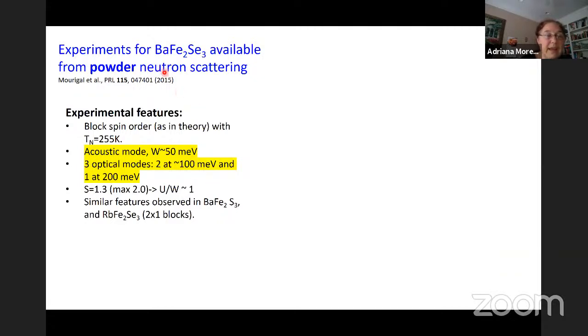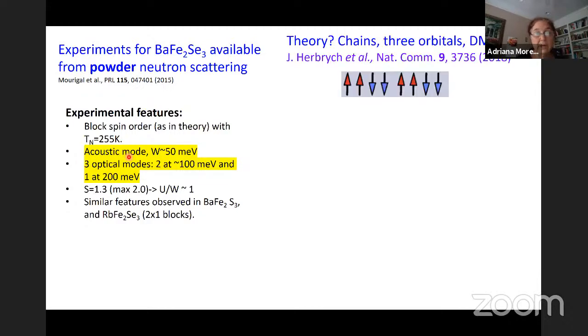Let's see what other properties experimentalists have found in the ladder compounds, barium iron selenide. In addition to the block spin order, they studied S(Q,omega) and found an acoustic spin mode with a bandwidth of 50 millielectron volts, and 3 optical modes, 2 at about 100 millielectron volts and 1 at 200. So our next calculation was to try to compute S(Q,omega), which is not a simple task at all.